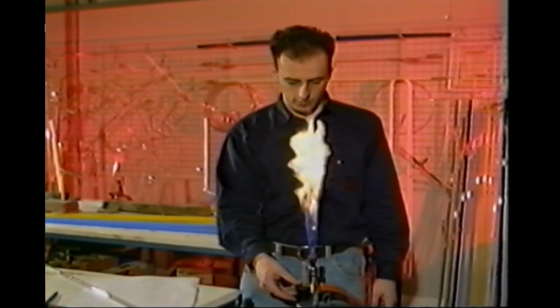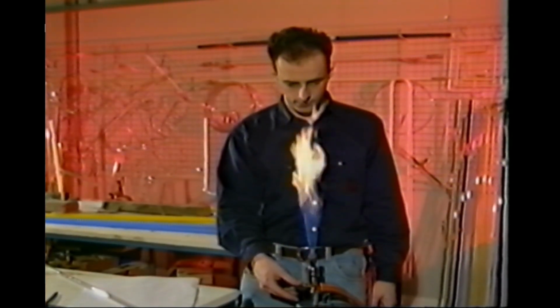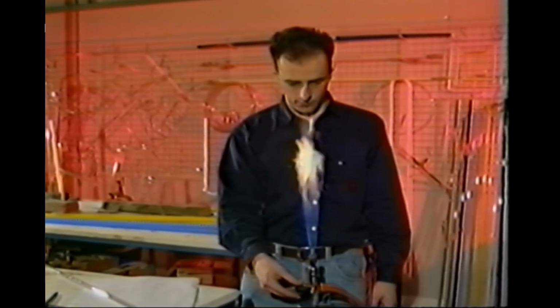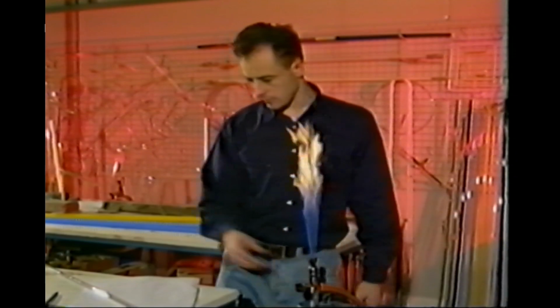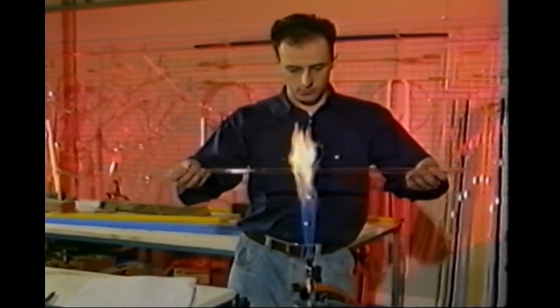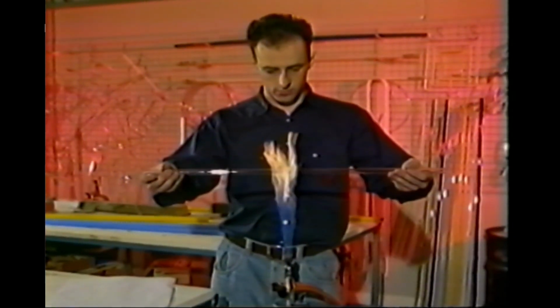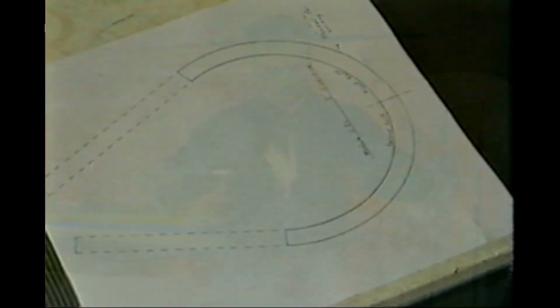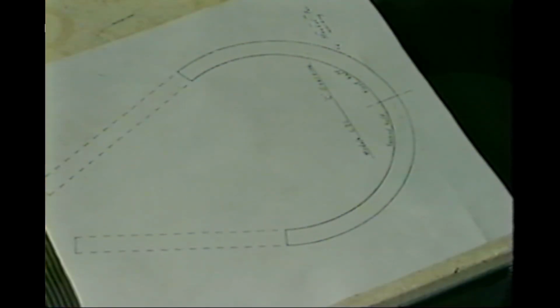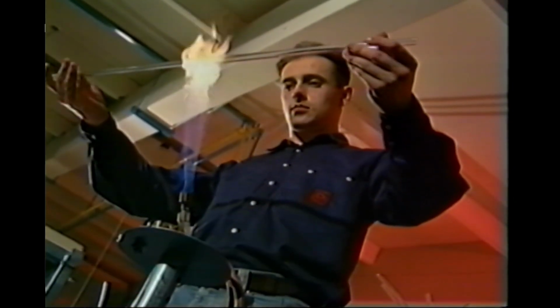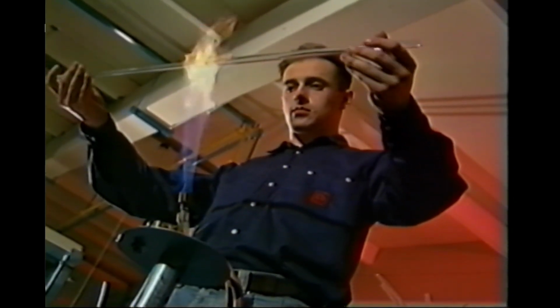Set up a large, wide, soft flame with a blue color base, but with a yellow top area. In slow bending, the glass must only be melted to just soften it. If it's melted too much, the correct shape cannot be achieved. We will now bend the curve to fit the right side curve of a letter C. Place the glass in the flame two-thirds of the way up its overall height.